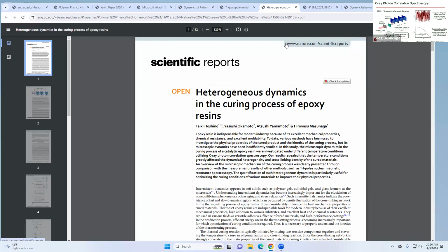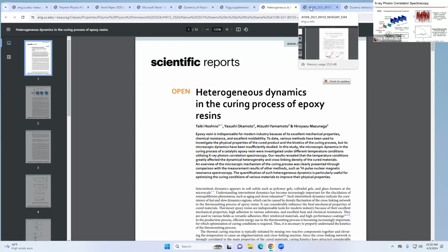So we use a data processing technique or protocol to get out the information in this real space regime. And the way we do that is we take these speckle patterns, we look at how the intensity varies as a function of time, and we get these kind of crazy plots here. But what we can do is we can integrate across that, and basically we look at the temporal variation in the intensity at some scattering vector Q on our detector, right? That's the length scale we're looking at. And then from that, we can calculate or generate what's called an autocorrelation function, which is going to correlate those intensity variations in time. And what that comes out to looks like an exponential decay like this.